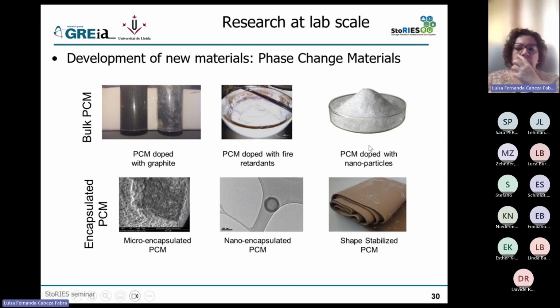We have also doped PCMs with nanoparticles to achieve different objectives. To me, the main challenge of adding nanoparticles to any storage materials is ensuring that the nanoparticle will stay distributed in all the material. And especially when we talk about bulk materials. In the lab, we start working with very small quantities. But if you think of the final application, for sure you will have at least liters, if not cubic meters or tons of material. So to ensure that your nanoparticle is still distributed around all your tank, for me, it's a challenge. And it's a challenge which is more difficult to fulfill than the change of the property of the material itself.